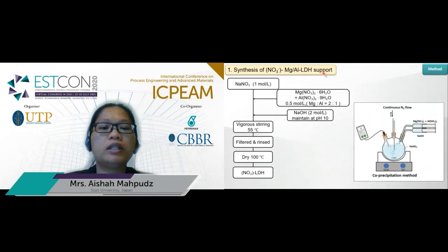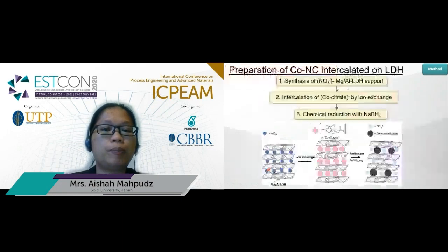For the synthesis of the nitrate type of magnesium aluminum LDH, in a typical procedure, a mixed metal salt containing magnesium and aluminum nitrate of molar ratio 2:1 is added dropwise into a solution containing sodium nitrate, and at the same time, sodium hydroxide at 2 mol per liter is added to maintain the pH at 10. Throughout the dropwise addition of magnesium and aluminum nitrate, the solution is vigorously stirred at 55 degrees Celsius. It is then filtered, rinsed and dried at 100 degrees Celsius. I refer to the sample as nitrate LDH for simplification.